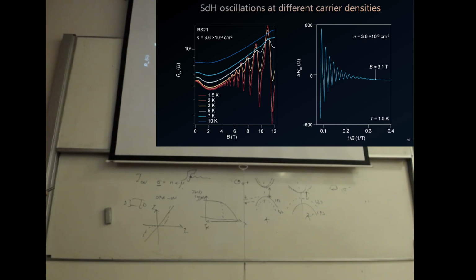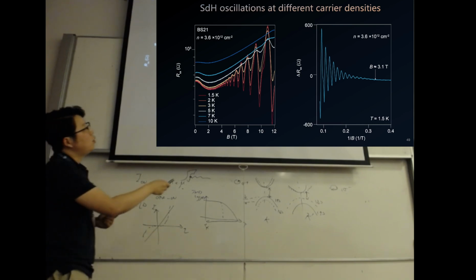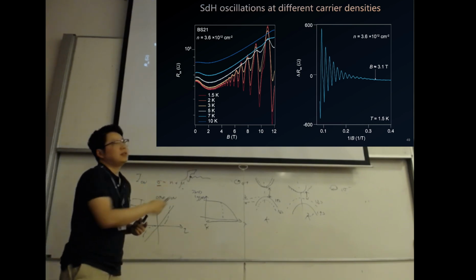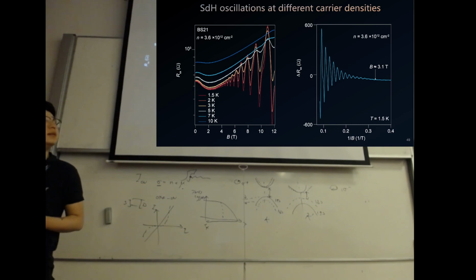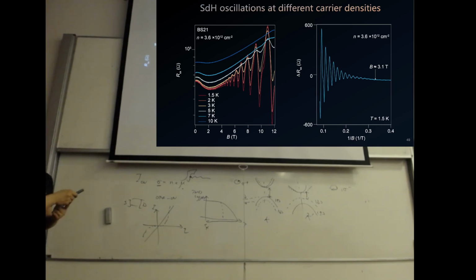If we plot the amplitude of these oscillations as a function of 1/B, we can have another estimation. The point where the oscillation disappears defines the quantum mobility. That means to have SdH, your mobility is there. In our case, here it's about 3,000. Just 1/B, 0.3 times 10 to the 4th. 3,000 is the quantum mobility in this sample at this doping level.